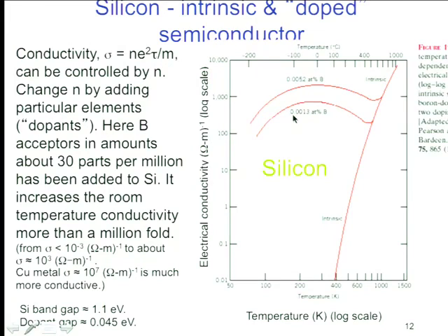Namely, if you look, the temperature is actually increasing this way. And you see that the conductivity goes up first, because what's happening is you're thermally exciting the electrons. You sometimes have a picture something like this. The boron is here. You're exciting a hole into the boron. Then the electron goes into the boron, and the hole starts moving. So that's thermally excited. But once they're up there, then the heat does you harm in a way, because then the lattice is moving, and those moving holes start to scatter. So the conductivity turns down. So that's the explanation of that curve.